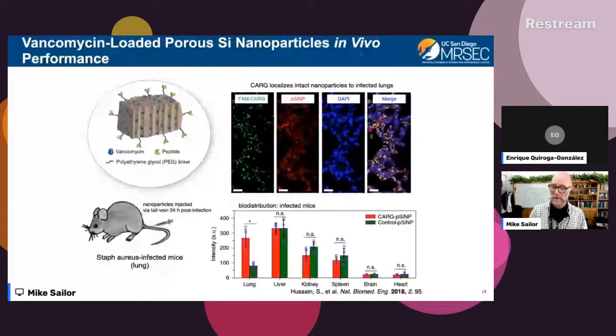You can see that the red bar highlighted for the lung is much larger than the green bar highlighted in the lung. What that says is this targeting peptide has some selectivity for getting into the lungs of infected mice. What's not shown here is we did a control experiment with mice that did not have any infection. And in there, we don't see any targeting by that peptide. The peptide doesn't help that particle get into the lungs any better if it's there or not there. So this demonstrates that the peptide that Erkki Ruoslahti gave us actually does have some selectivity for getting into the lungs of infected mice.